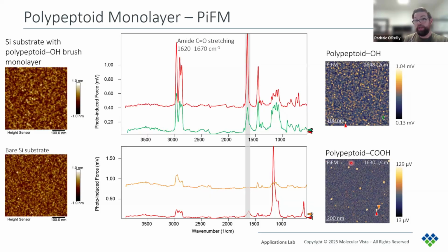But for the polypeptoid-OH, we see a monolayer. The PiFM image map at 1648 shows there's some variation. There are some brighter spots, some darker spots, but the spectrum on the darker regions, which is the green spectrum in this case, still shows the carbonyl peak, but it's just weaker. So the change in this intensity is most likely due to changes in the packing density of the molecules in the monolayer, but we are seeing pretty uniform coverage across the surface.